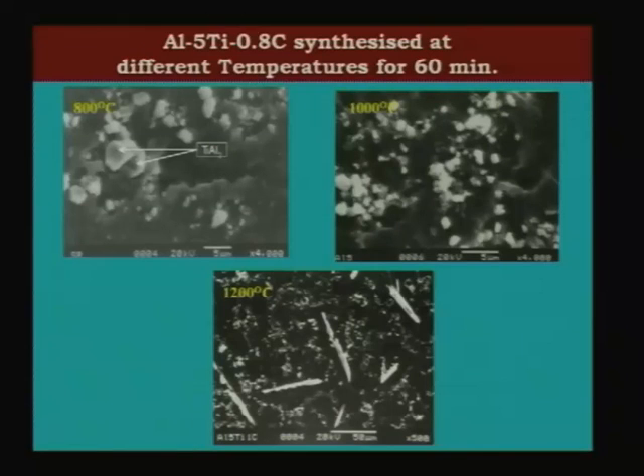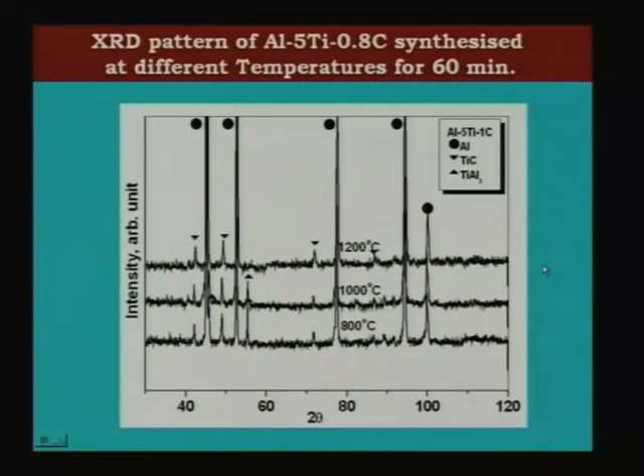The only difference as far as the temperature is concerned is, at low temperature TiAl3 forms in the form of blocky type of particles, more or less equiaxed particles. At higher temperature TiAl3 grows as needles or plates, because TiAl3 has a tendency at higher temperature to grow in one particular direction, the 001 type of direction, to give you this kind of flake, plate-like or needle-like morphology. So, what is important to realize here is that you always end up with some TiC particles plus TiAl3. So, this clearly shows you why we should control the composition. Then go to the next one, we will come to that a little later.